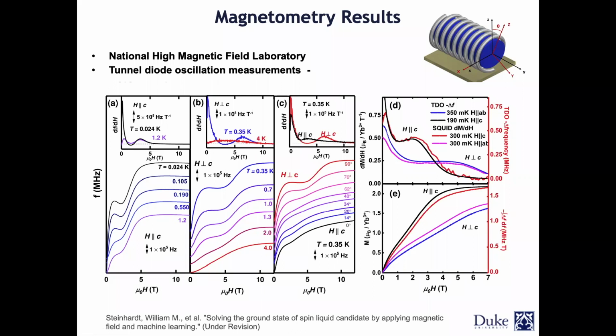But what is important about it is that it's actually very high resolution. So if there is anything that cannot be seen with different methods, it can be seen here. And the size of the sample that we can use can also be small. Here, for example, you can see the frequency of the TDO, let's call this TDO, for H parallel to C at different temperatures, and for H perpendicular to C, again at different temperatures.